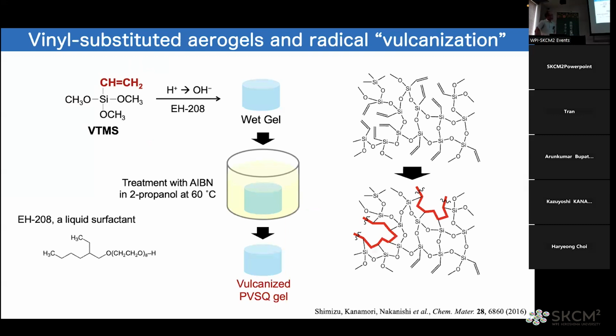Okay. So from the same vinyl functionalized precursor, but this is only from the trifunctional alkoxysilane, we can prepare also the transparent aerogel by a similar process. And here you can see the network from this precursor. There are a lot of vinyl groups. So after the preparation, we can make the hydrocarbon chains by the radical reaction in a solution. So we can alter the mechanical property of this material.